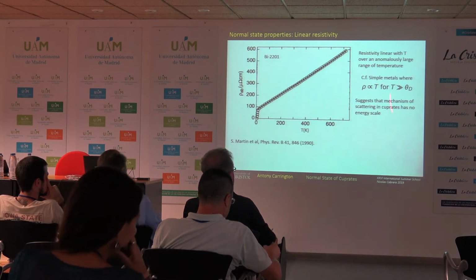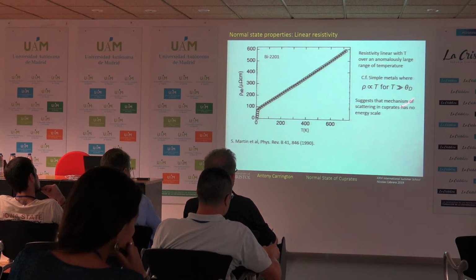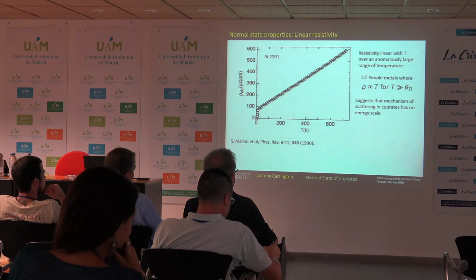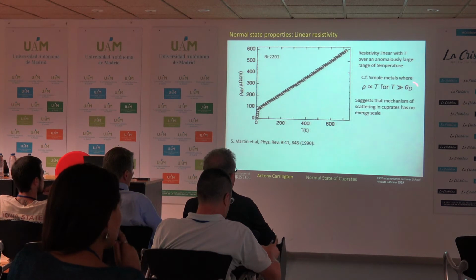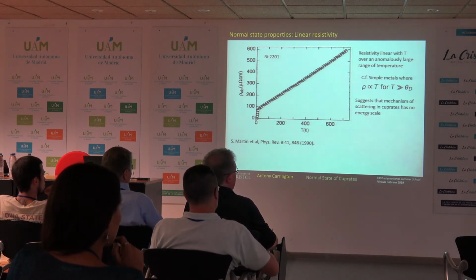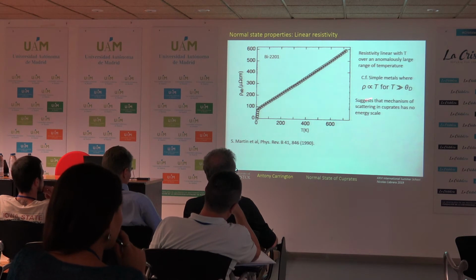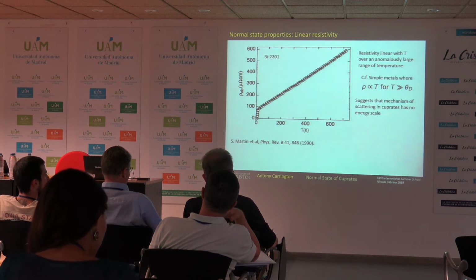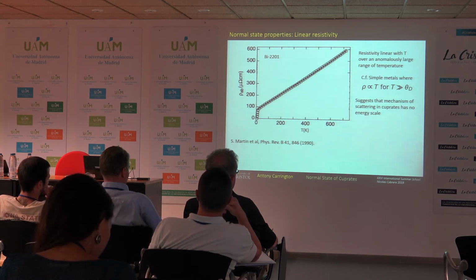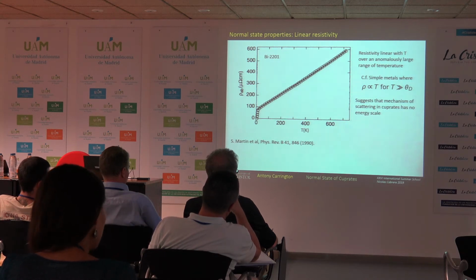This means that if you think about a general theory where you've got electrons scattering off some bosons, electron-phonon scattering would be an example. In electron-phonon scattering, you have an energy scale, and the energy scale is the Debye temperature. And if you're at a temperature well below the Debye temperature, it's no longer linear in T, right? Because at high temperature, the scattering is basically determined by the number of phonons. And at low temperature, the energy structure of the phonons becomes important. And that would be true for any other scattering mechanism.